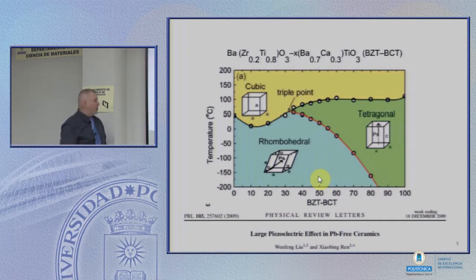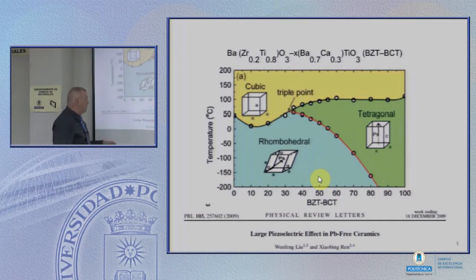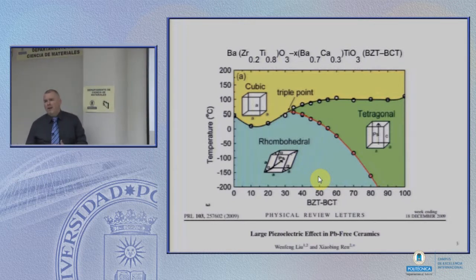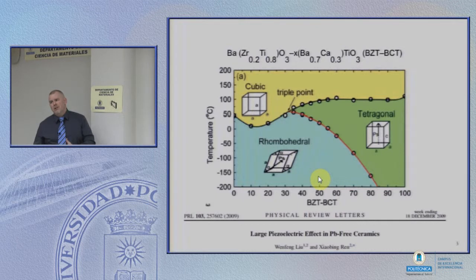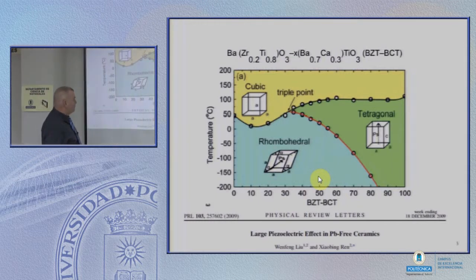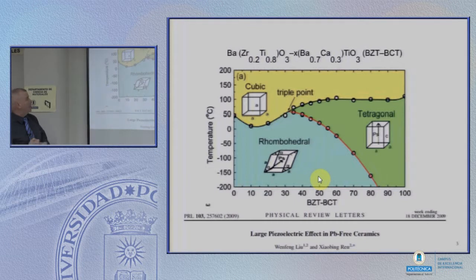All that Xiaobing Ren and his colleague Wenfeng Liu did was say, all right, what would we want to do if we had these materials to produce a case wherein we could get good performance? So they tried to imagine phase diagrams that would look like the ones that we see, for example, for the PZT materials. So they just made the material. Apparently, they made the material on one of the first experiments, made some measurements on it, and they were very surprised at the measurements. It was presented about a year later for the first time in public.